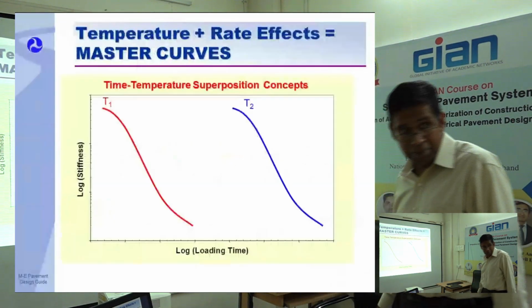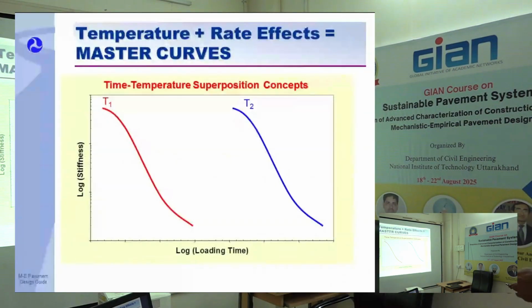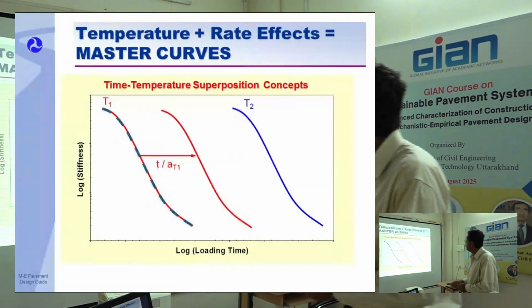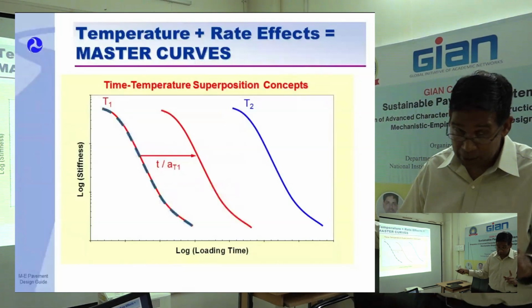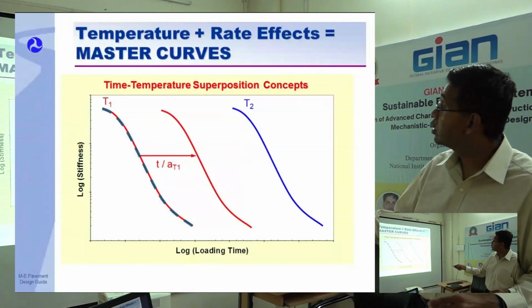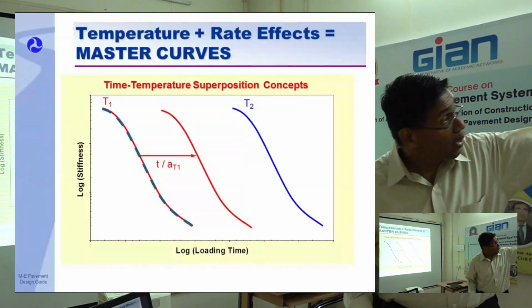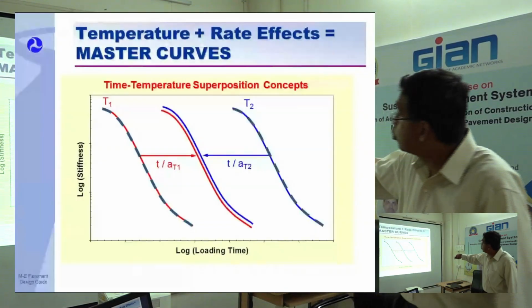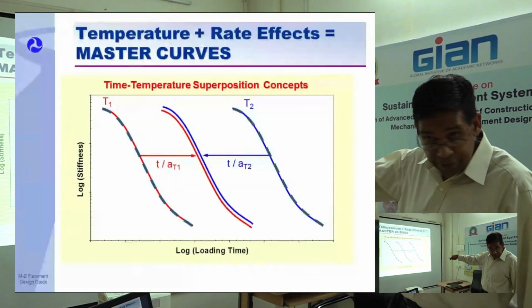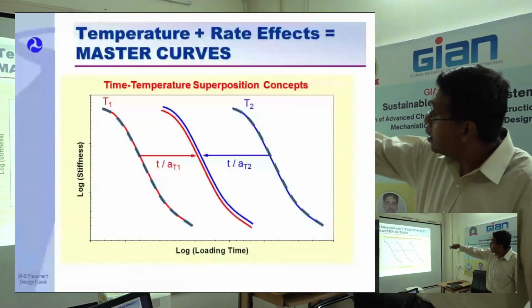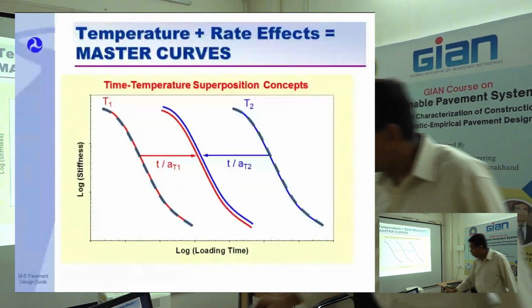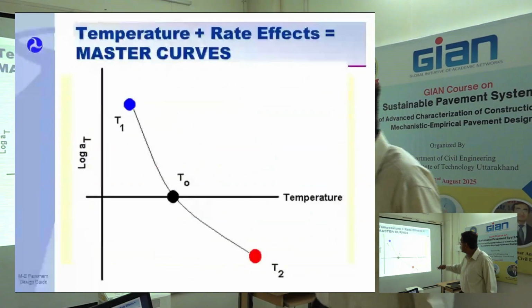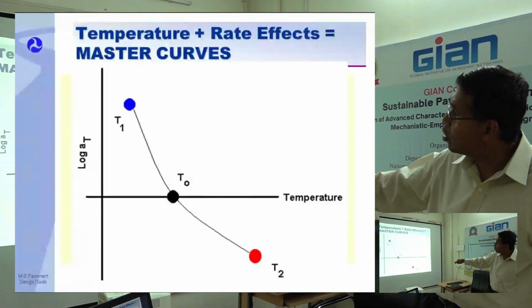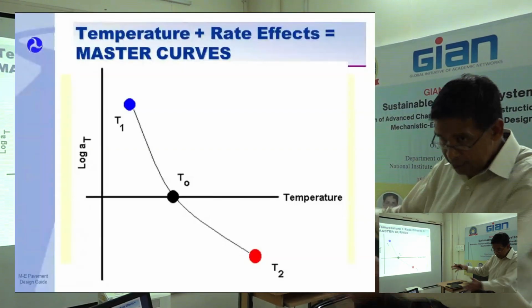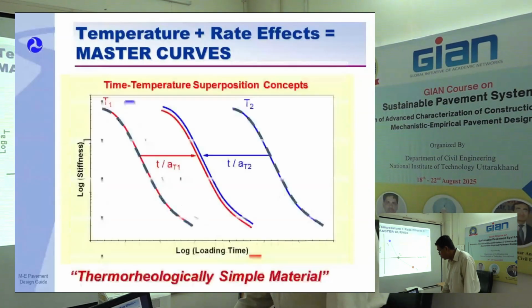Right here, this is more graphics for you. So right here, you have temperature 1, you have temperature 2, right? You can move it horizontally, not vertically. You cannot change that. Horizontally, you can move on both sides. This is log modulus versus loading time. And you move to the left if it is colder, and to the right if it is warmer. So you can move to the right and you get one reference temperature. You can do multiple temperatures and then you can shift. The shift at reference temperature is 0. The shift at other temperatures is left or right. That's your shift factor. That's a lot of other math there.